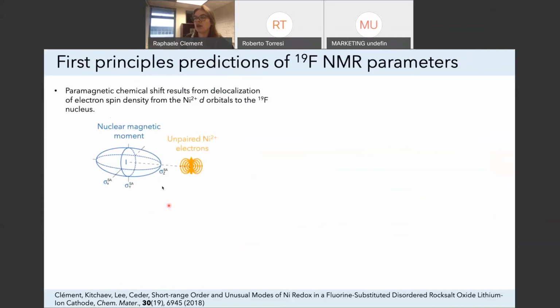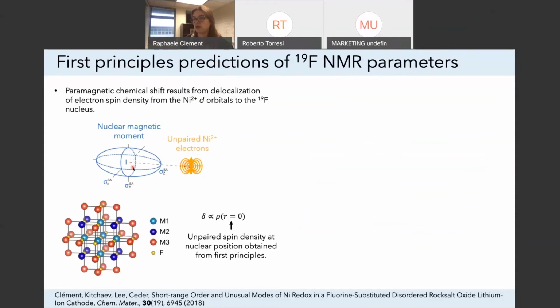Again, what we are looking at here is the strong interaction between our fluorine nucleus that we are probing with NMR and its interaction with nickel ions that are nearby, and especially the electrons in the d orbitals of nickel that are delocalized onto the nucleus of interest. And so that delocalization process leads to a non-zero spin density at the position of the nucleus, shown here. And this is something we can calculate from first principles, and it gives us an idea of the chemical shift that we would expect for that particular environment.